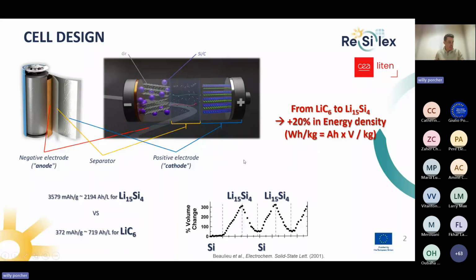So I will start with a basic introduction on batteries. It was slightly done already by Hamid, but to remind you, in a battery we have a negative and a positive electrode. They exchange lithium, and it's compensated in the external circuit by a current. When you are in discharge, for example, lithium goes from the negative electrode to the positive electrode. For safety reasons, we don't have lithium metal in a battery, and the lithium is intercalated or alloyed in active material. In a conventional battery, it is graphite at the anode side, as said by Hamid, with low potential, around 100 millivolt for graphite, and a capacity of 372 milliampere hour per gram.